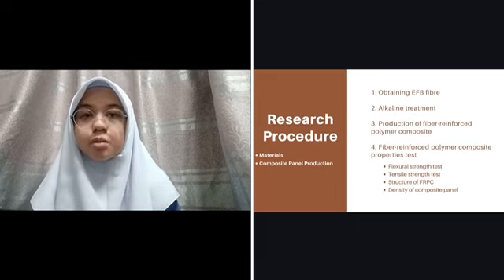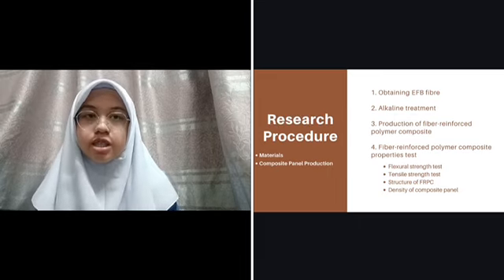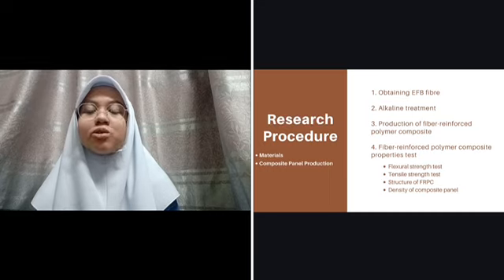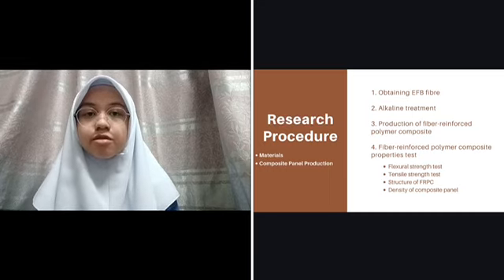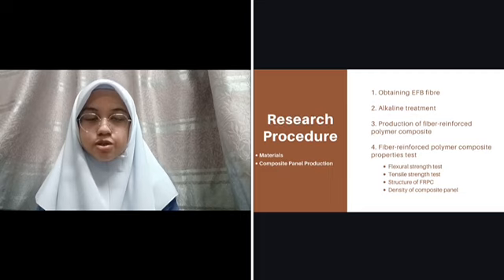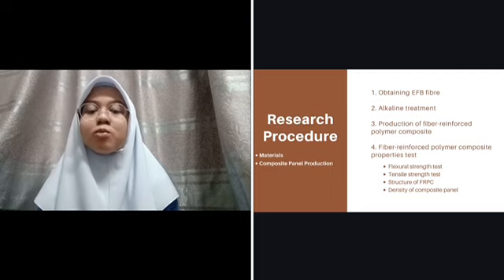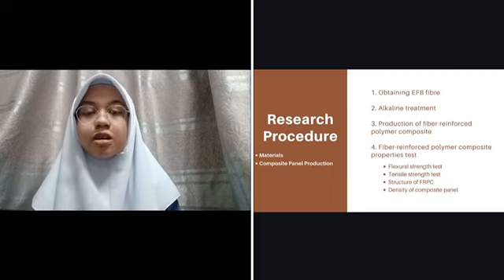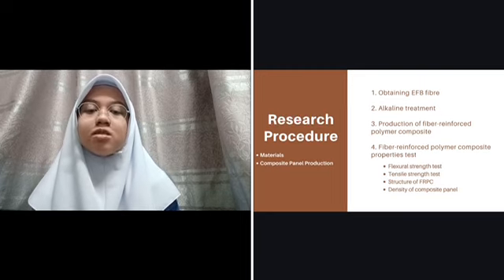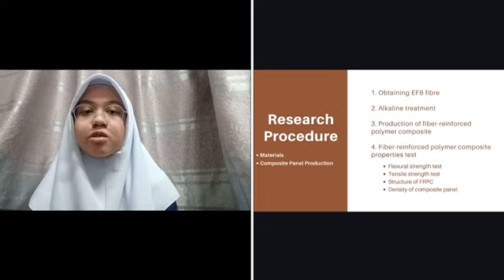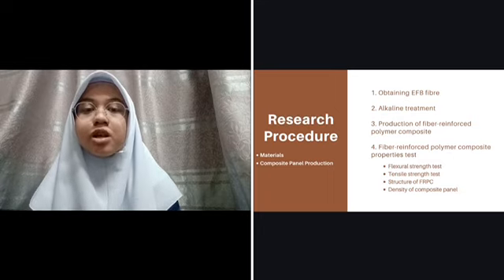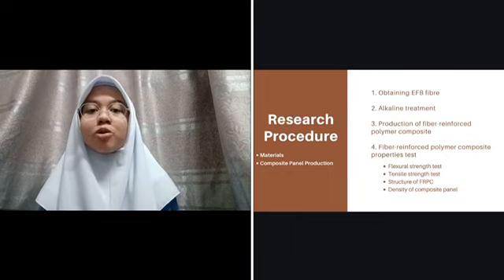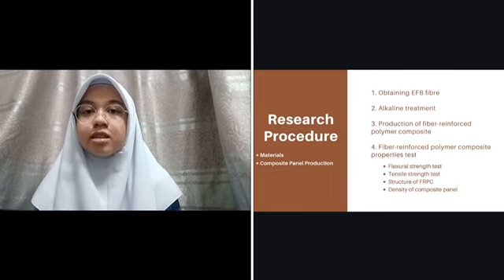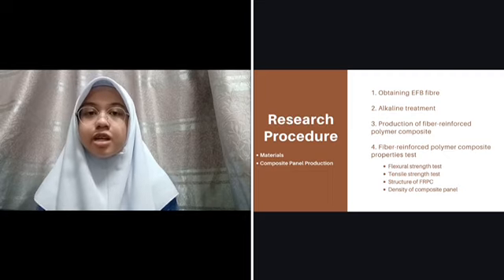And next, we applied alkaline treatment on the EFB fiber. This was done to increase the surface roughness of the fiber and to reduce its hydrophilic nature, since most natural fibers are hydrophilic. We immersed the EFB fiber in 1 liter of 0.75 mol per dm cubic of sodium hydroxide solution for 24 hours. Then, the EFB fiber was taken out, hand washed with distilled water, and air dried.